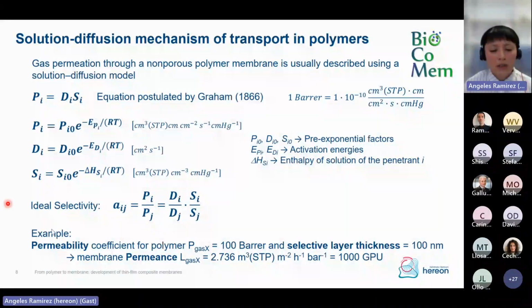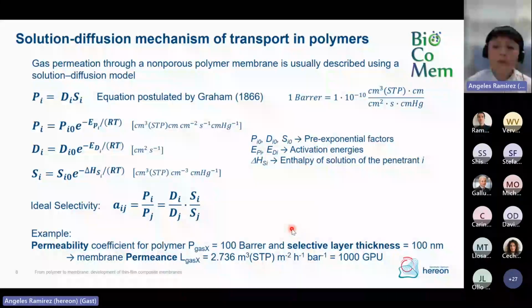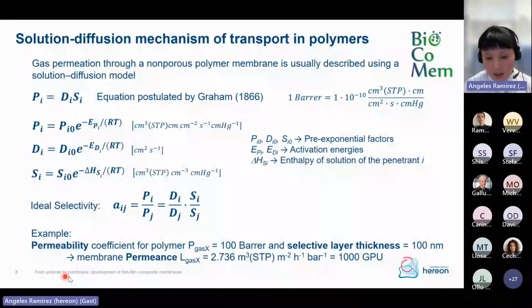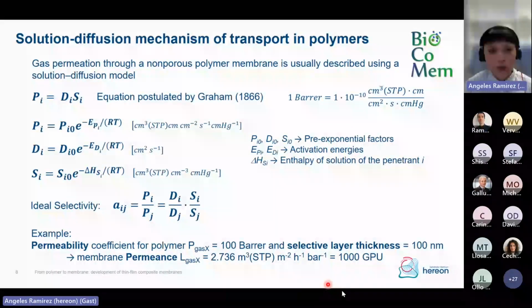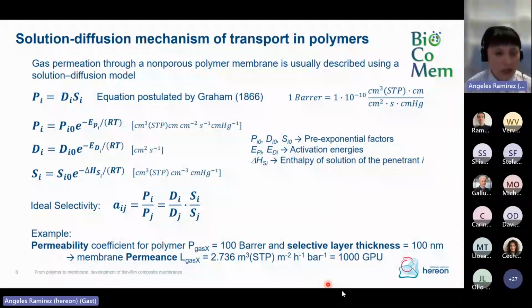And now an example here about the units that we use for these separations. If we have a permeability coefficient for a given polymer and a given gas, so a gas X, for example, of 100 barrer, and we have a selective layer thickness of around 100 nanometers, we would get a membrane permeance of around 2.7 cubic meters per square meter hour and bar, which will be equal to 1000 GPU, or gas permeation units.